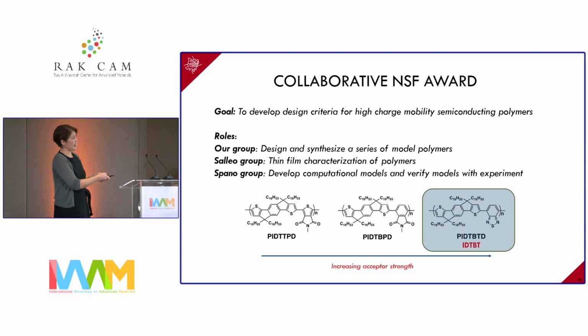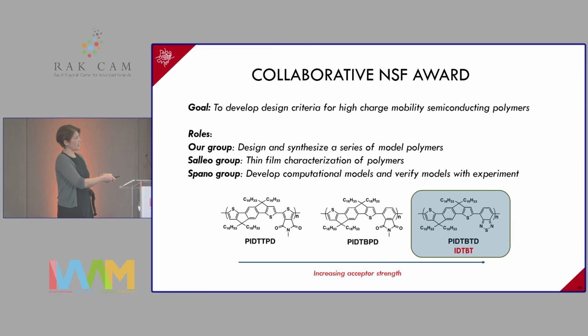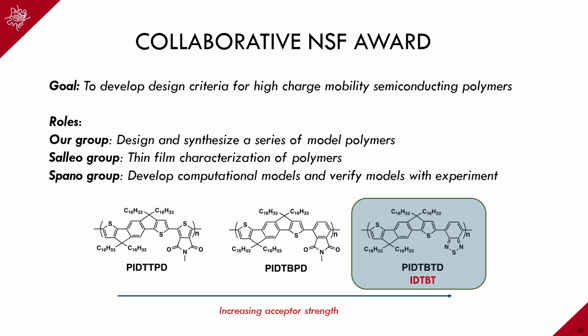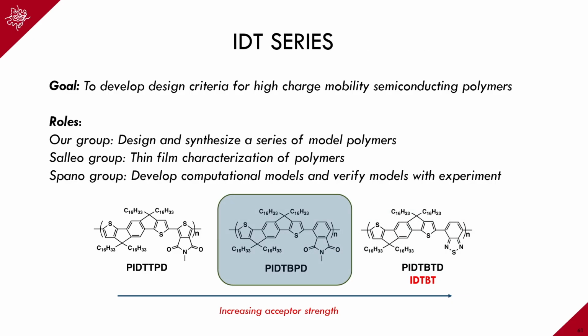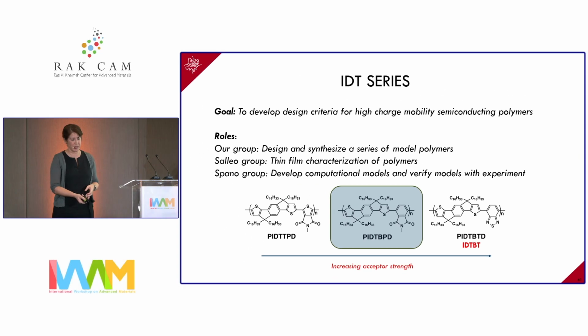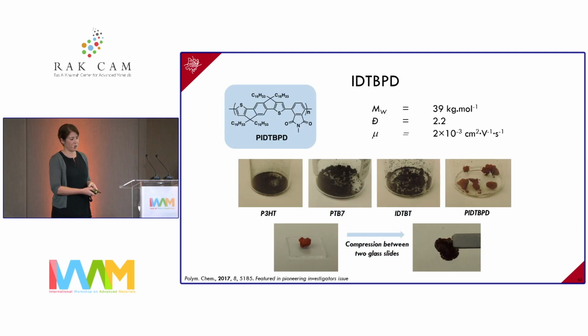So here again, this is the polymer that I just showed you. But what we decided to do was to make a series of these polymers where the only thing that we're changing is the co-monomer that we're adding. This huge fused ring is still a common factor in all our polymers. When we synthesized these three series, we saw something that was very, very strange about this one particular polymer in the middle. And that was to do with the physical properties of it that we saw.